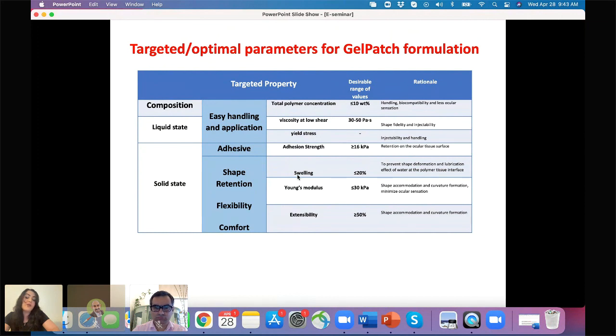We want a hydrogel formulation that swell less than 20% to prevent shape deformation. And also the Young modulus and extensibility of the hydrogel is extremely important, because the hydrogel should be flexible enough for the shape accommodation and curvature formation, and at the same time it should be stable at least for a month in vivo to have a drug release profile over 1 month. So by knowing these characteristics, we design our gel patch that give us all these properties.